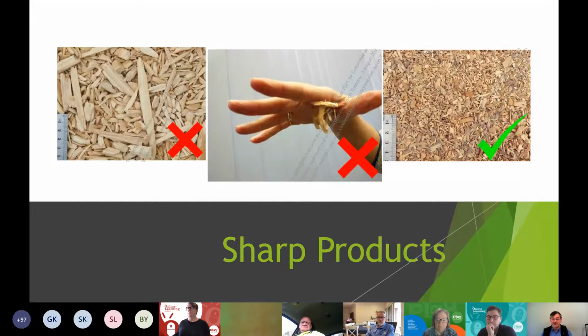A lot of the time people are trying to sell garden mulch into the industry where it's just chopped up anything, and they send it off and get it tested. So then I talk to them and tell them how to actually get the product to a standard. They need to put it through a hammer mill, and they need to round it and roll it or put it in a rumbling mill, where they put it in a big mixer with steel shot that rumbles it and softens it up and grinds it. And then out of that, you only get about 50% of the product that's any good to go into a playground. So they have to do a bit of work to get this material to comply. The soft bark mulches are usually better, but they end up with a bit of whitewood in it, and they end up with splinters in it as well.